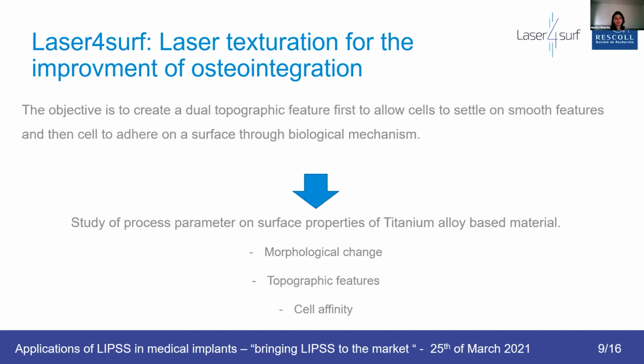So in the framework of the Laser4Surf project, we were studying various process parameters of the surface. We evaluated the morphological change, the topographic features, as well as cell affinities. We decided to use titanium-based implants because it's one of the most widely known metals used for medical implants, which is very biocompatible, but also quite inert toward cell osteointegration. So let's say it's a negative control, in the sense that it does not bring any functionality on the surface by itself. So we can see how the surface treatments give improvements to cells and to topographic features.